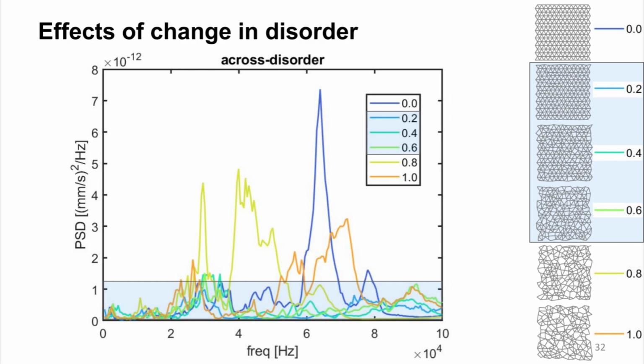I would like to compare the power spectral density curves of metamaterials across different disorders of the metamaterials that I have. And here is an image of all the different metamaterials of different disorders and the curves I get. I find that the Bragg peak for no disorder is completely suppressed for 3 of the metamaterials of smallest perturbation 0.2 and next perturbation strengths of 0.4 and 0.6. However, I find that for some of the higher perturbations, the strength of amplitudes in power spectral density curves again becomes comparable to the peak of the Bragg peak of no perturbation around some of the frequencies. And I would come back to this later after checking for dependence of these on tension.